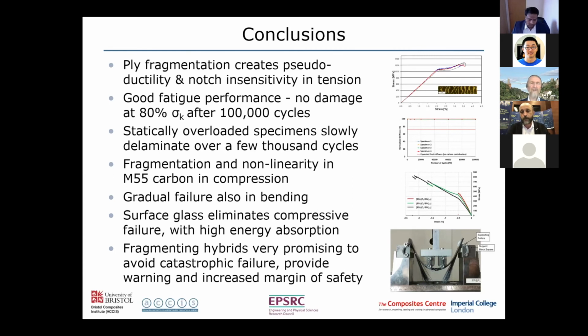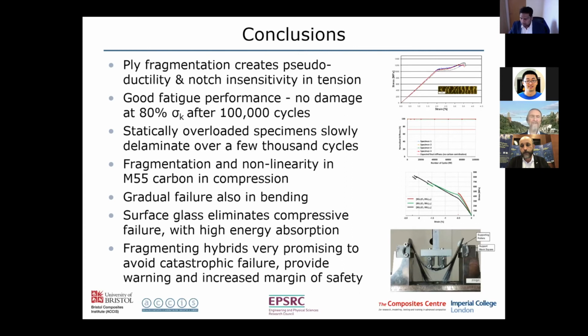So I think it's a very interesting idea. I think there's scope for a lot of further work in this area, and maybe we can collaborate on this. Interesting. We have done little bits where, for example, we have pre-cut the carbon fibers. So rather than putting continuous carbon fibers in there, we pre-cut them, and that gives us another parameter to vary. Because we can get the delamination starting straight away if we wanted, because the fibers are already cut. But we've really only just scratched the surface.